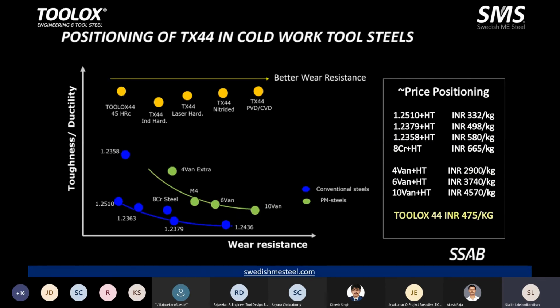So we keep saying that the material Toolox 44 is very highly tough as well as ductile. You find that not only against D2 or a modified D2 version, even for your PM coated steel there is a possibility to replace it with Toolox if your application has been chosen wisely. As you can see, with laser hardened Toolox 44 or PVD or CVD coated Toolox 44, you find the toughness values to be very high, as well as the wear resistance also very high, even compared to both your conventional steels as well as your powder metallurgy steels.